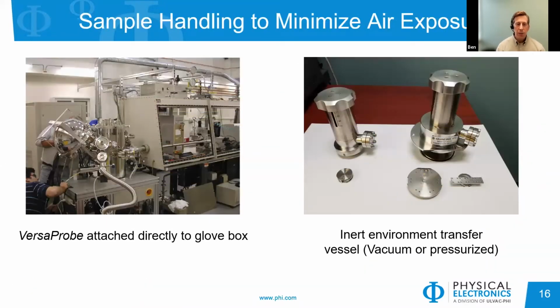And so sample handling can be done a few ways. In production facilities for lithium-ion batteries, typically these are dry rooms where the humidity is controlled to a very low level. If you're working more at an R&D level, you might be working in a glove box, which is typically going to be an argon glove box, again, with low humidity and oxygen. So for our systems, for example the VersaProbe, which is our multi-technique XPS, we can hook this directly up to a glove box. And so you can process your material in the glove box on a transfer arm and then move it into the system. We also do have transfer vessels, which can be used to move outside the system, but within either a vacuum or a pressurized atmosphere of, say, argon, to minimize any kind of air exposure that might degrade your material.